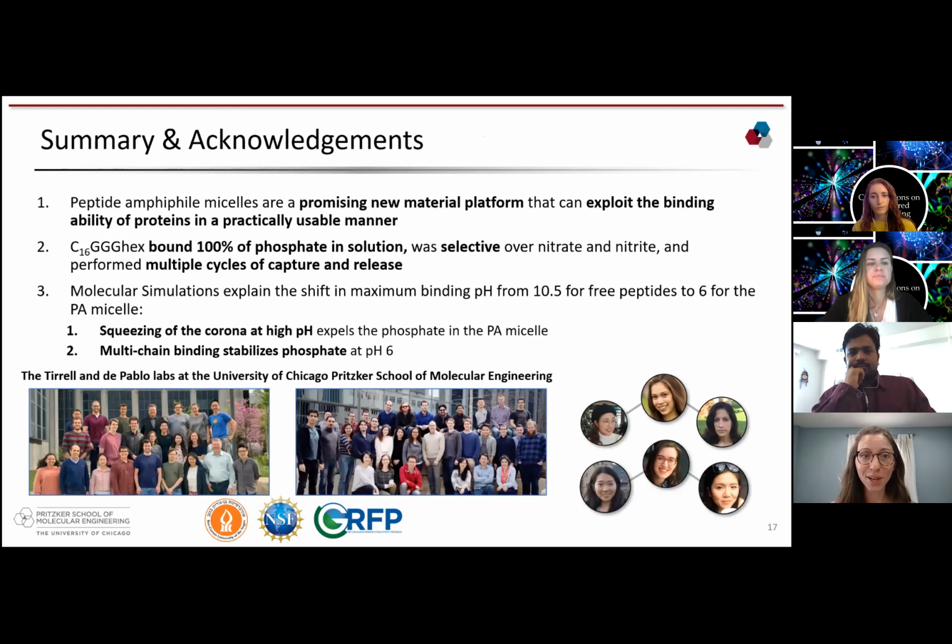So that's the end of my talk. To sum it up, 3 main points. The first one is, very generally, if you're going to walk away with something, remember that peptide amphiphile micelles are a new interesting material platform that can exploit the binding ability of proteins in a way that's practically usable, so we can actually reclaim the phosphate rather than just having it be in solution. Second, this material bound phosphate 100%, was selective, and also performed multiple cycles of reuse. And then third, the molecular simulations captured this interesting binding shift from the maximum binding at high pH to pH 6 through the squeezing of the micelle corona at high pH, and then the multi-chain binding at pH 6.